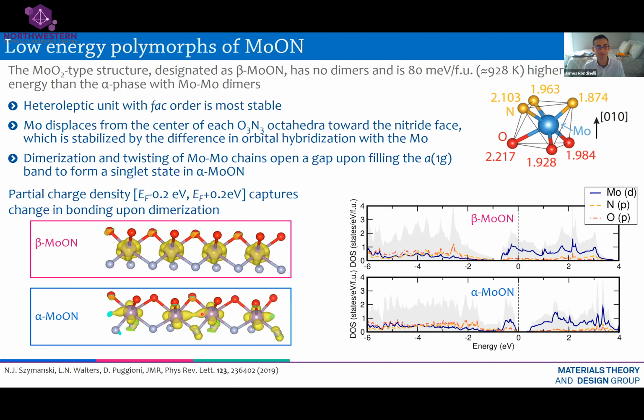And this is the formation of a covalent bond, or the signature of the singlet state. And this is what leads to electron localization that prevents the hopping of electrons in the material, which would cause the transport to not occur. And so this is the character of the insulating state.